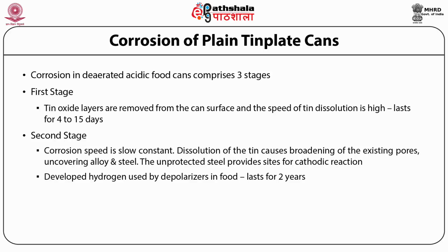The third stage is shown by high rate of tin and iron dissolution. As large areas of steel are exposed, hydrogen is produced at a faster rate and accumulates in the can, causing swelling.